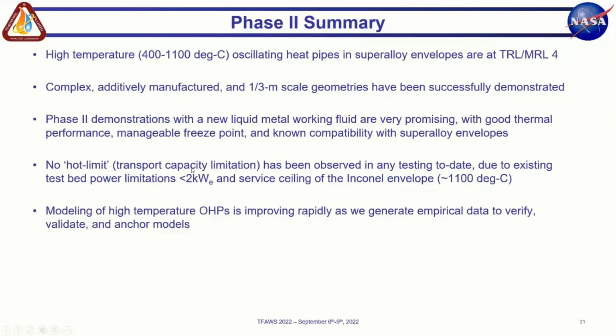No hot limit, meaning transport capacity limitation of the structure due to very high input flux or some other condition, has been observed in any testing to date. Somewhat unfortunately, we would love to be able to validate the predictions of how much heat these structures can transport, but we just weren't able to get there with the existing test bed. Power limitations allow us to push up to about 2 kilowatts electrical, and we also weren't able to show the temperature limit of these liquid metal working fluids, because we aren't able to push above probably 1100 C on the Inconel envelope, so perhaps 1000 C fluid temperature. We would have to go up to maybe a niobium alloy type envelope in the future to really see where we run into transport capacity limitations just due to temperature.